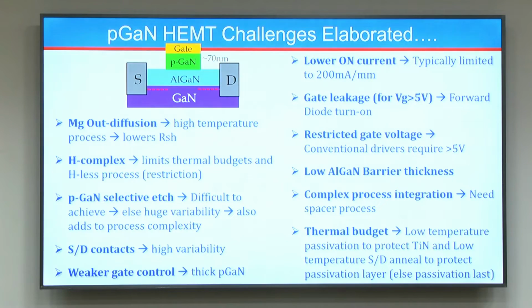As I said, complex process integration, even the gate requires the spacer process to avoid any sidewall leakage. So even the sidewall, when you etch the pGaN, you have a lot of these sidewall traps. So these sidewall surface traps can also conduct, so you have to even passivate those sidewall surface traps. Thermal budget, as I said, a lot of these processes are low temperature process, and if you don't control or optimize the thermal budget, you may have other kind of problems.